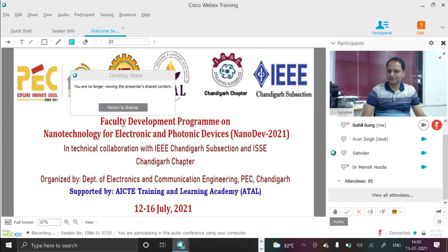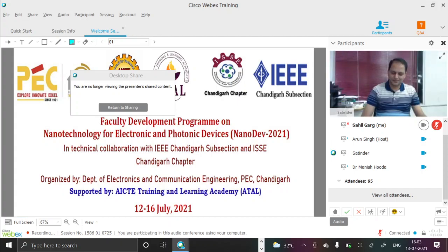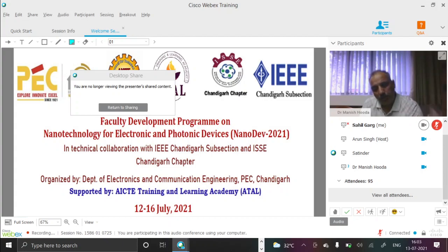Thank you very much, Dr. Satinder, for accepting our invitation to share your recent work on photoresist, e-beam resist, etc. I hope participants will benefit from it and start using this next generation resist technology for their device fabrication. I think this has also been trialed at SCL Mohali, right, sir? Yes, sir. The DUV resist was developed by IIT Mandi, and indigenization was done for this resist for the first time. It has been developed for deep UV lithography up to 48 nanometer, which has been successfully demonstrated, and it is at par with the international supplier of this same kind of photoresist, which is a proprietary item. I am very sure that the EUV resist would also come under this category, as the results are very encouraging.